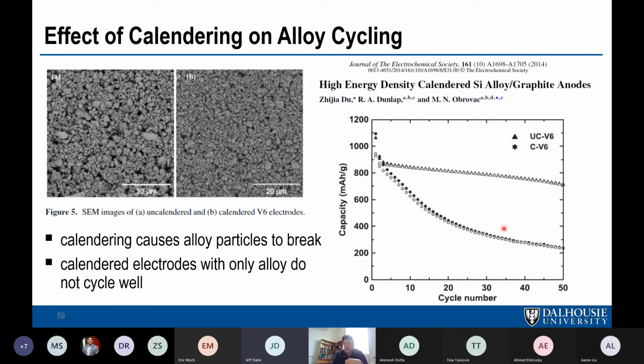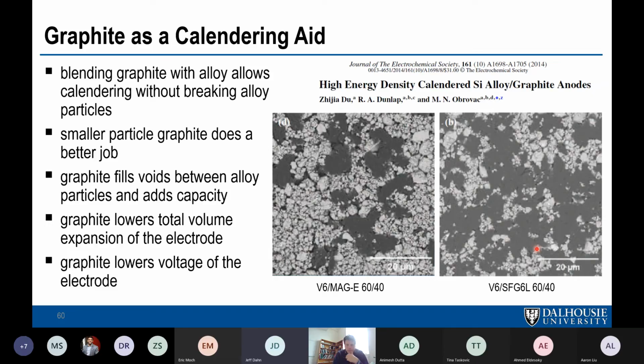And the cycling is terrible. So this is before you calender it, you got half decent cycling. And after you calender it, the cycling is very poor. So to try to improve that, you add graphite, which is a calendering lubricant. In some commercial cells, you can even find graphite in the positive electrode because it can help densify the coating. And that graphite can help the particles slide by one another. This is, again, before calendering and after calendering. And if you add enough graphite, you can still see some big rocks, some big particles that haven't broken because the particles were able to move around. There was enough graphite in there.